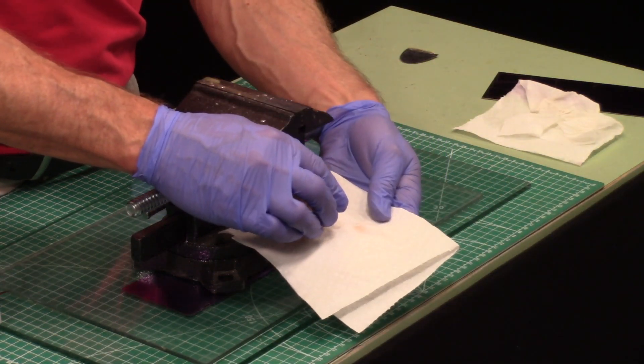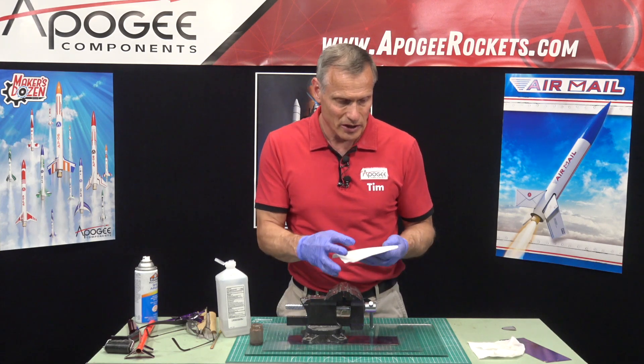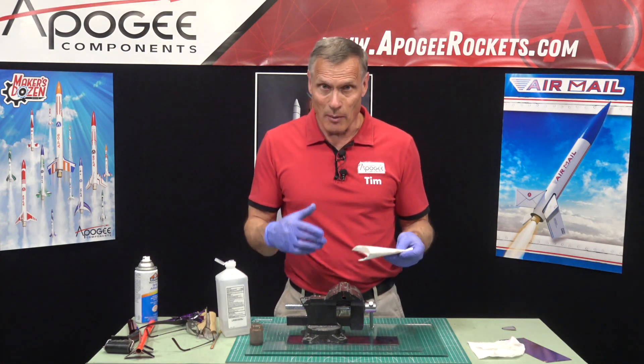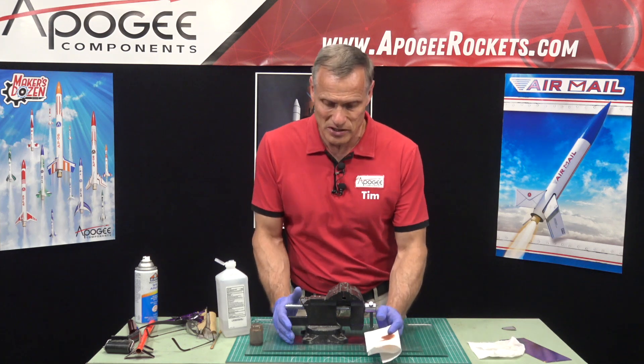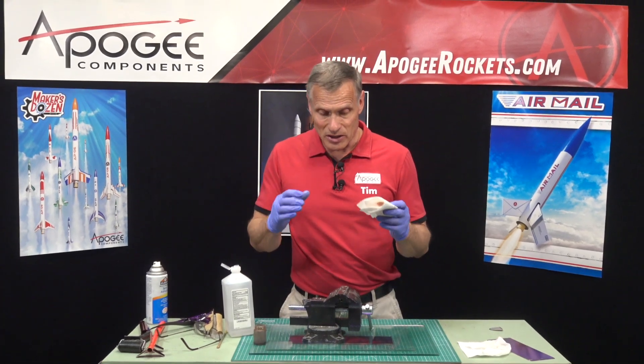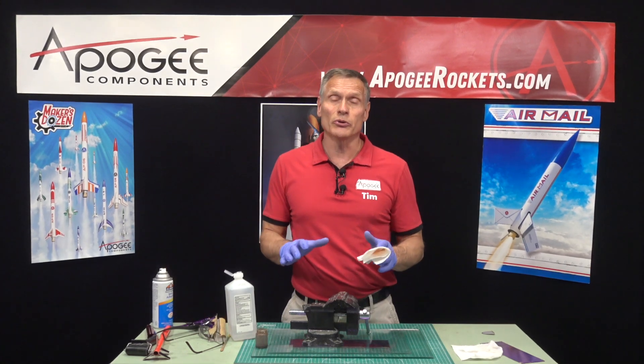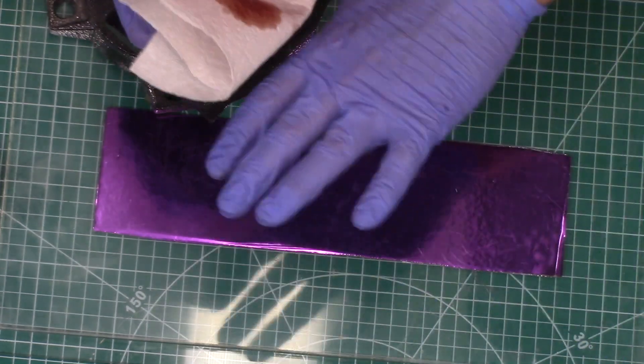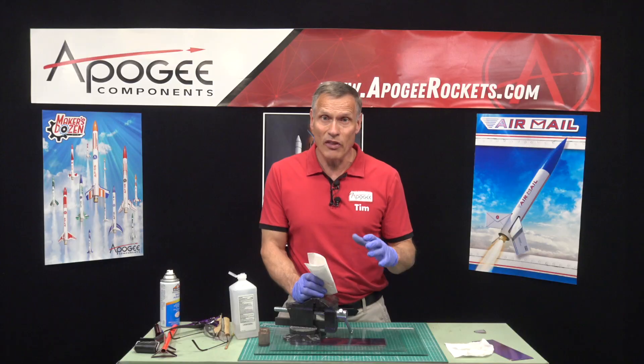What I do is put a little bit of leftover epoxy on a paper towel — when that is hard, I know that the piece underneath is hard too. If you have a vacuum bag system, you can also throw that into a vacuum bag and suck all the air out — that will help to get rid of any air bubbles. I can press down on the glass and see where there are some little lumps. The more weight I can put on and the more I can suck out the air, that's going to help make it smoother.